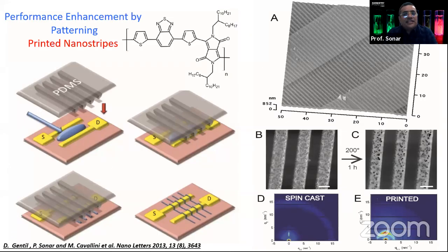And here, looking at this polymer, this is in collaboration with Italian colleagues. We did some nanoimprinting, putting this polymer down as a solution between the source and drain gold electrodes. By using a PDMS stamp with protrusions and a spacing between the two protrusions of the stamp, we got these wonderful nano strips across the source and drain. Here you can see the same image where all the polymer nano strips are in between. This is a gold electrode, and between them we have a polymer nicely organized.